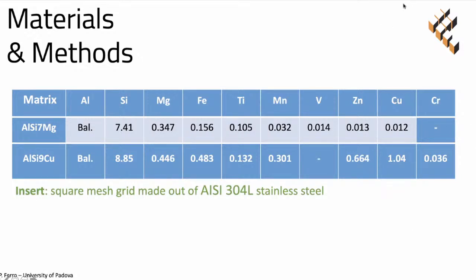Silicon is well known to increase the fluidity of the alloy, while copper increases the mechanical properties of the alloys. Another element is iron, that is in greater amounts in the second alloy. But iron introduces some intermetallic precipitates that may cause a brittle fracture of the alloy itself.